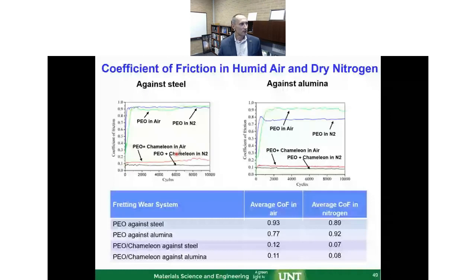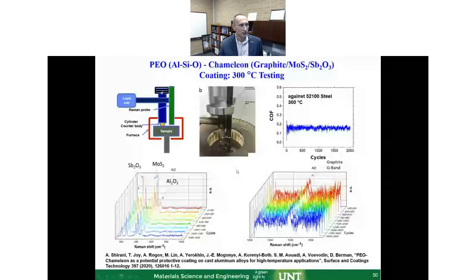As soon as you put it here on the top, the friction drops down very low. And this is against steel, and this is against alumina. Of course, in dry nitrogen, it gets even lower and much more enduring because molybdenum disulfide kicks in and works in there. All right, so this is the room temperature.